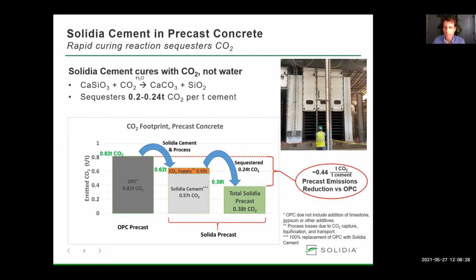An additional reduction in footprint occurs due to CO2 sequestration during curing of Solidia concrete. Here we're using 0.24 tons of CO2 per ton of cement. This results in an emissions reduction of 0.44 tons of CO2 per ton of cement. I should note that the small parasitic losses occurring during the curing process are not included. We'll use this number, the 0.44, on the next slide to calculate the potential impact of this technology on industrial CO2 emissions.